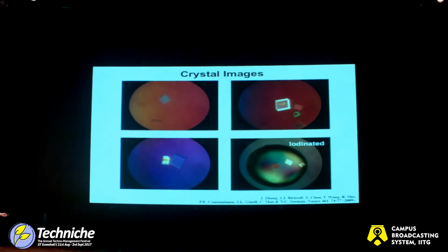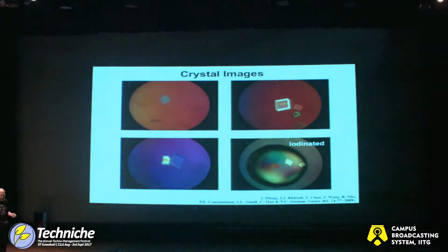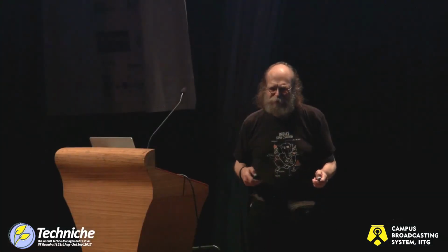Okay, so by putting these things just together in a pot, we were able to make macroscopic crystals. These are things you can see with your naked eye. They go anywhere from about 0.2 of a millimeter when they behave properly, all the way up to even a millimeter on occasion. You can see over here that the scale bars are 200 microns. This is probably 300 or 400 microns across the diagonals here, and large crystals, and we know where all the atoms are because we put them there.